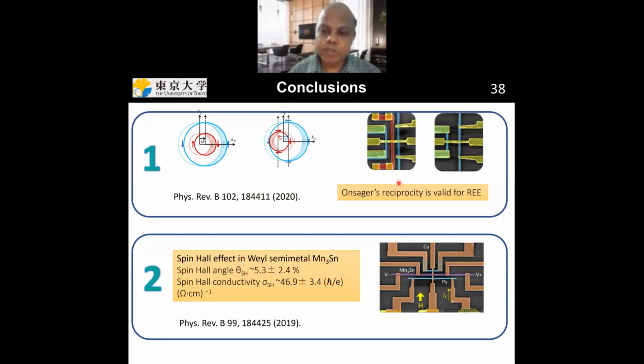And I saw that Onsager reciprocity is valid in the Rashba-Edelstein effect. And the second, I saw the non-local spin Hall device can be used to study spin charge conversion in Weyl metals, for example, manganese tin. And I found a very large spin Hall conductivity comparable to theoretically predicted values.